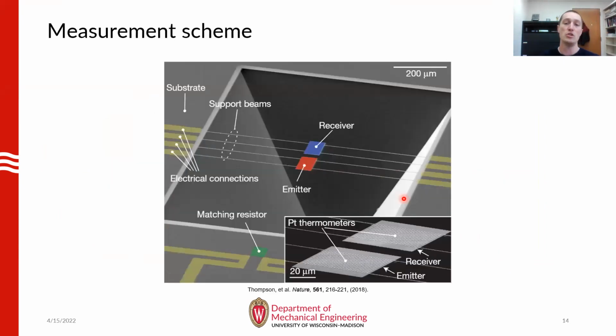On this slide, I want to show you a measurement approach I developed that allowed me to quantitatively measure the radiative heat transfer rate between two individual nanostructures. The approach relied on fabricating the two suspended nanomembranes you see in this electron micrograph. Both membranes are comprised of silicon nitride, and they're suspended by 4 long support beams. These membranes are also coplanar with one another, and they're separated by a fixed gap of 20 microns, which ensures that they're in the far field of one another at room temperature. That ensures that no evanescent waves can contribute to the heat transfer between them.